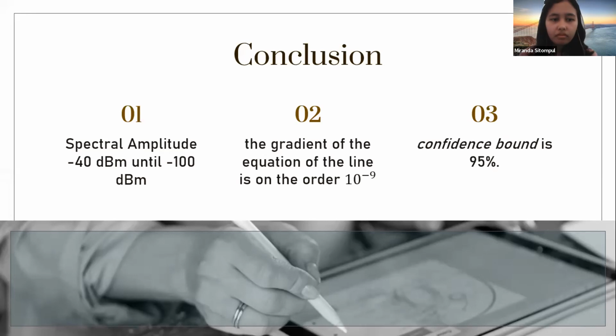And second, based on the line equation of each measurement curve, a small gradient is obtained, on the order of parts per billion. This gradient shows that the effect of temperature on the signal measurement result around the Timor National Observatory area is not significant and can be ignored. And the third is that the confidence bound value is 95%.